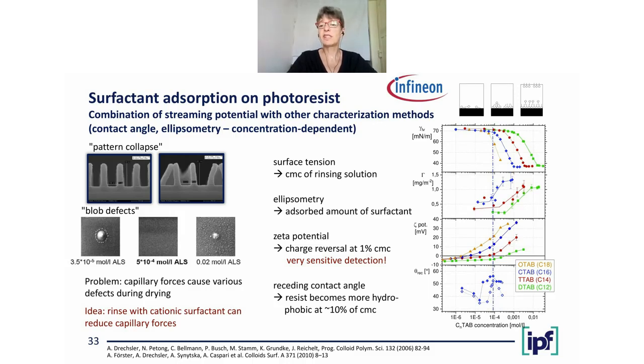And you can see that the Zeta potential is the most sensitive method to detect the adsorption of the cationic surfactant. Already at very low concentration, we see a charge reversal in a concentration range when only single surfactant molecules are adsorbed on the surface. And finally, we found out that at a concentration of about 10% of the critical micelle concentration, we have a maximum of the contact angle, and this helped us to reduce the capillary forces and also prevented the defects.